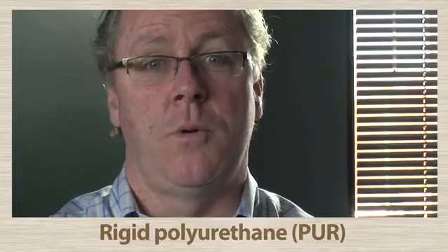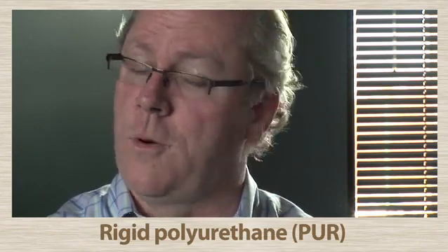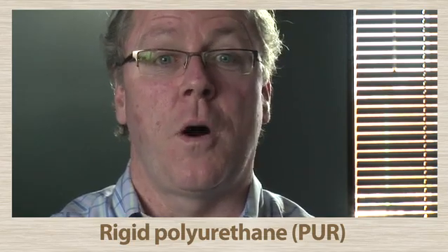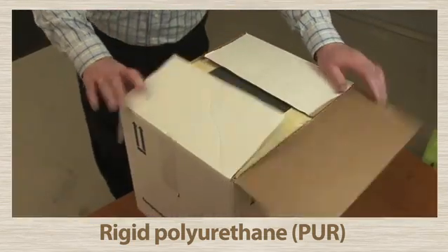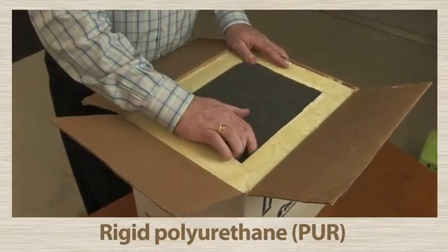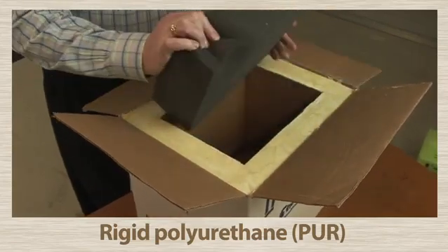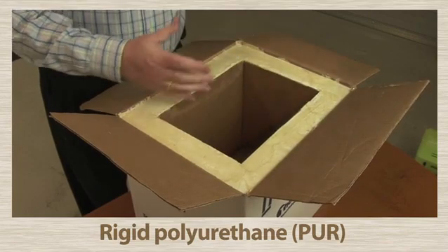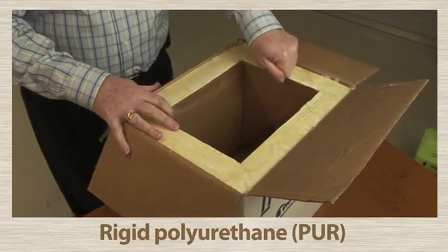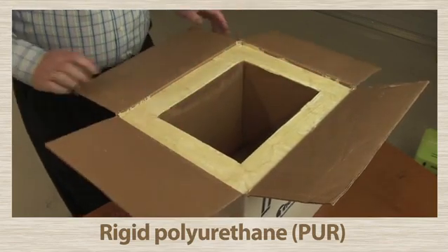So getting back to solid materials, we'll next take a look at rigid polyurethane. The trapped freon gas in PUR has a much lower thermal conductivity than air, and the lower the thermal conductivity, the better the insulation. PUR, as a result, has an R value of about 7 for every 3 centimeters in thickness of material. That's about twice that of EPP, EPS, or even air.